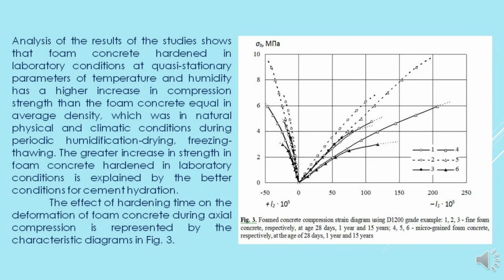Analysis of the results of the studies shows that foam concrete hardened in laboratory conditions at quasi-stationary parameters of temperature and humidity has a higher increase in compression strength than the foam concrete equal in average density, which was in natural physical and climatic conditions during periodic humidification drying, freezing thawing. The greater increase in strength in foam concrete hardened in laboratory conditions is explained by the better conditions for cement hydration. The effect of hardening time on the deformation of foam concrete during axial compression is represented by the characteristic